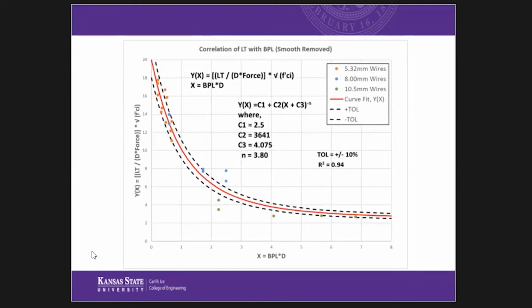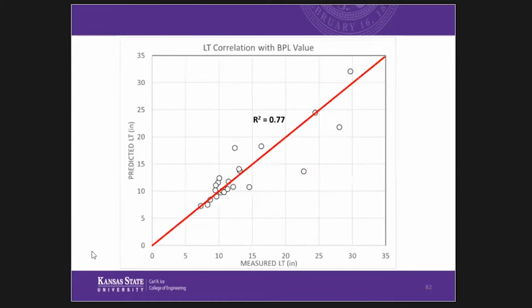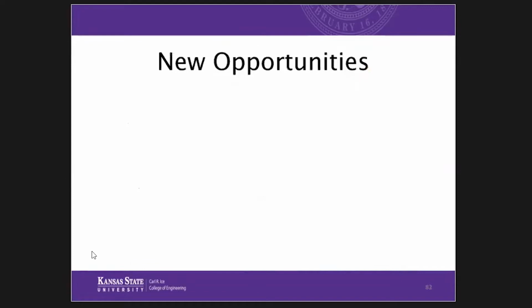The real test, again, is when you take this back to a linear plot, your predicted transfer length versus measured. Here, R squared is 0.77. And I think the reason we don't get as good a correlation is we're not taking into account the surface condition of the wire, the lubricants. We're only looking at the indents. But 0.77 across that entire body of data with many release strengths, many different diameters, I think is excellent. So I'm really excited about the steps going forward.